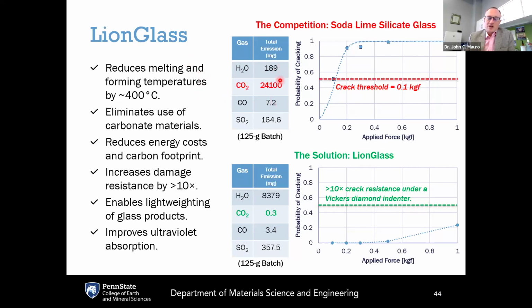So, for example, the upper table here shows soda lime silicate. What happens when you melt a 125-gram batch of soda lime silicate is that the carbonates decompose into oxides, and they release 24.1 grams of CO2. It's a huge amount of CO2 for that small batch compared to LionGlass, which eliminates the carbonates. The only CO2 here is due to trace impurities or CO2 that was already in the atmosphere. And so for the same size batch, it only releases 0.3 milligrams of CO2 from the batch to melt conversion process. It also dramatically reduces the energy consumption and associated costs and carbon footprint because of that temperature reduction.